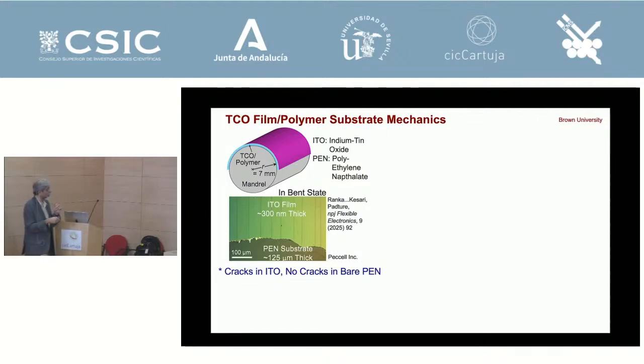And the polymer used here, what's called PEN, or polyethylene naphthalate, is extremely tough. So it's like your plastic wrap in your kitchen. It never fractures, it just stretches, right? But a ceramic, how brittle ceramics are, right? And so when you bend this like this, it's very normal to see cracks in the ceramic. So this is the ceramic, and this is the bare substrate with no ceramic coating there, right? And so you don't see cracks here. And so this is very normal.